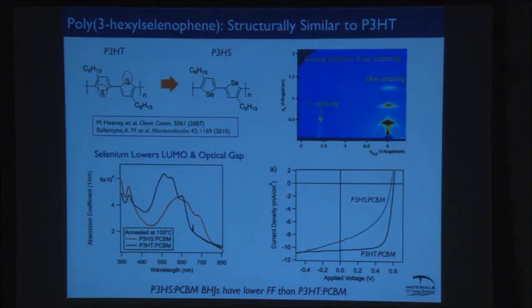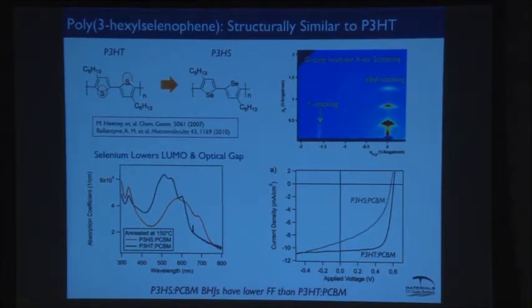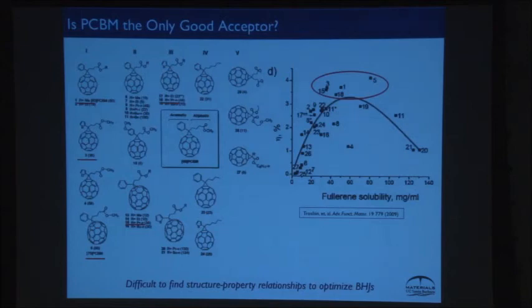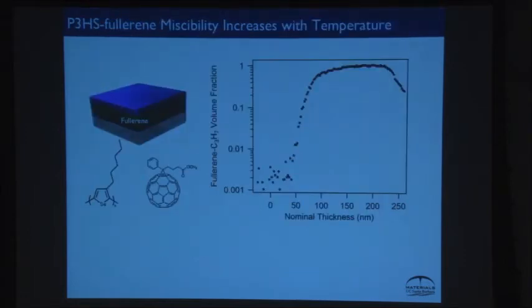But what always happened is that they worked on this, and they used the same acceptor all the time, and the solar cells were never better. They were always worse than the P3HT case. All they did was change one atom, and suddenly they just can't make a solar cell. There were like 6 papers written on this, where they never increased the fill factor, which really reduces the efficiency of this material. So we said, well, there are a lot of other fullerenes around, and people tend not to use them, because this fullerene PCBM that I keep showing you is the one that tends to work with everything. And there were empirical correlations around for other fullerenes, but it really wasn't so sure what to do to change that. So I asked Martin to give us some material, and we just tried some experiments.